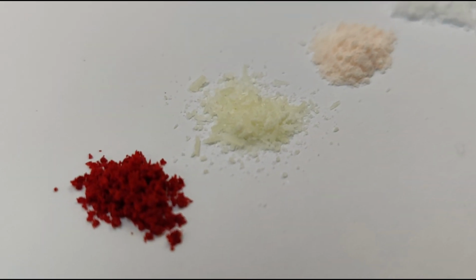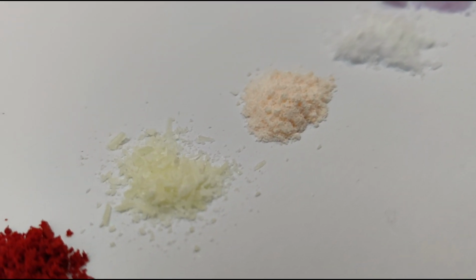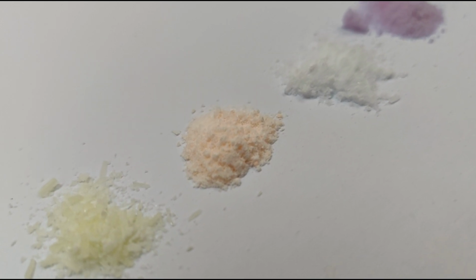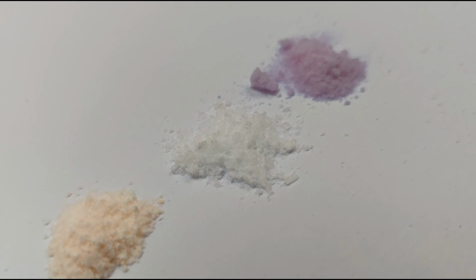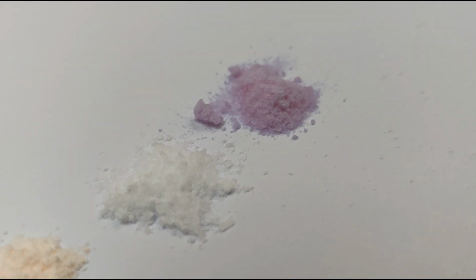Doping of BFO films with rare earth elements will also help us to enhance piezoelectric and photoelectric properties by increasing coercive field, limiting leakage current, changing carrier concentration, mobility, and so on.